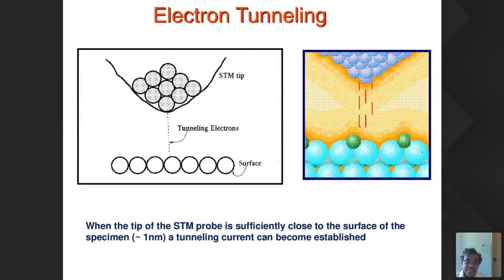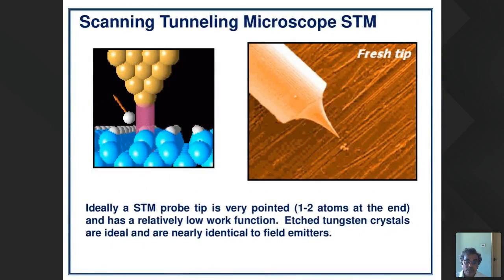These are the tunneling electrons, and this is the STM tip, and the surface. The tunneling current will pass between the sharp tip and the atoms at the atomic radius. A tunneling current will be generated when we go near the sample. Ideally, the STM probe tip is very pointed, with 1 to 2 atoms at the end. It has a relatively low work function. Tungsten crystals are ideal and are nearly identical to field emitters.